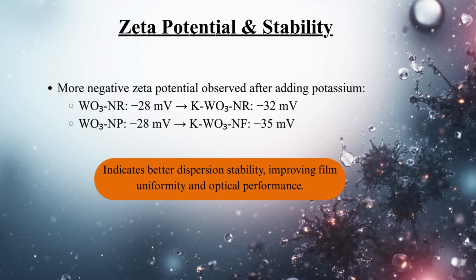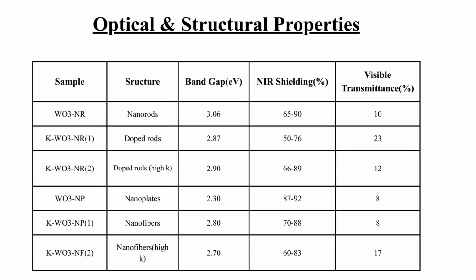Zeta potential and stability. The zeta potential showed that doping WO3 with potassium results in a more negative value. This indicates the KWO3 material has superior dispersion stability. This stability is vital for creating uniform thin films and maximizing the optical performance of the smart window coating.